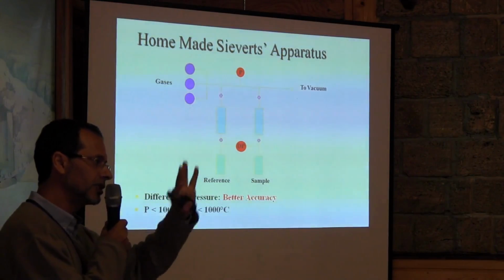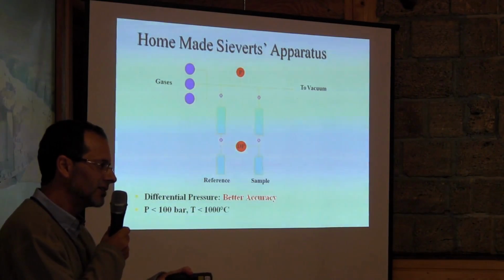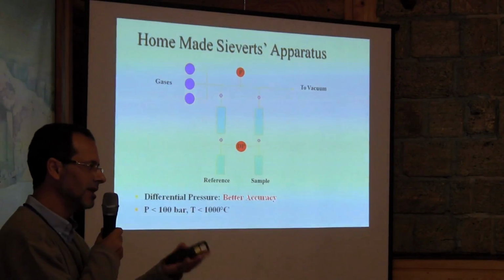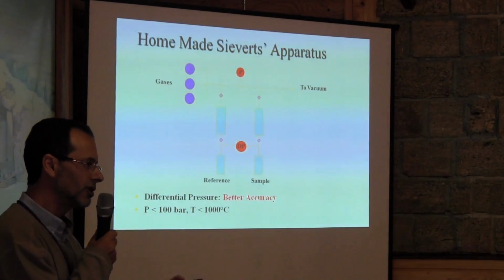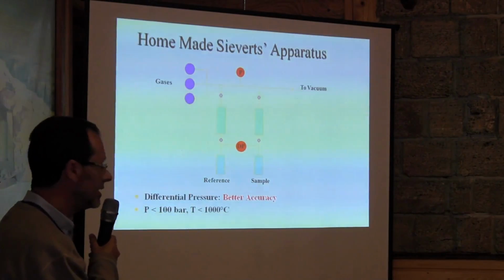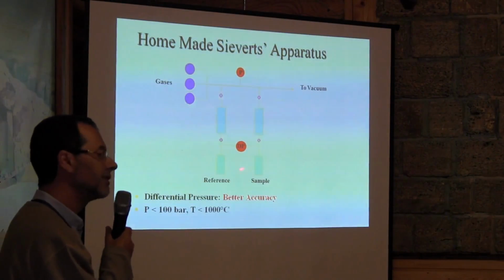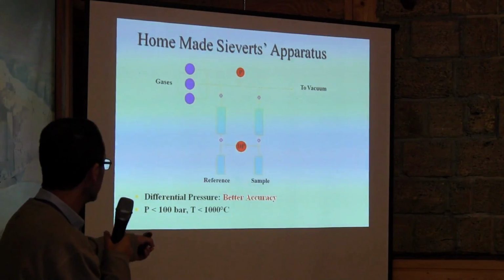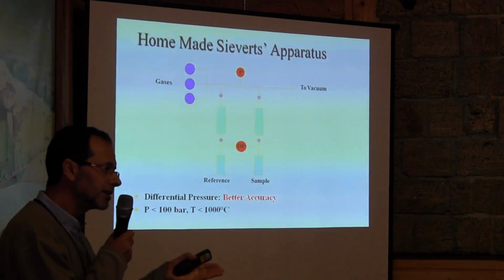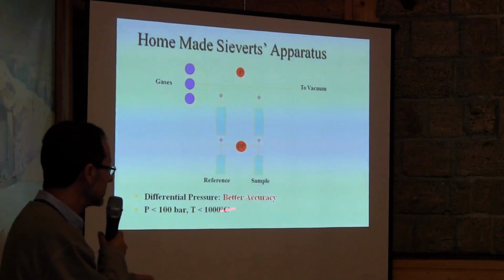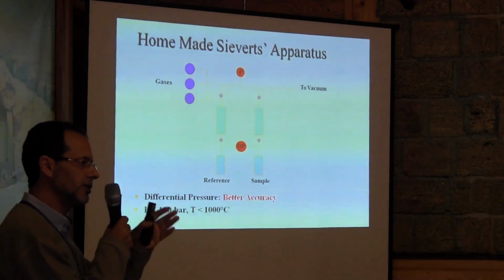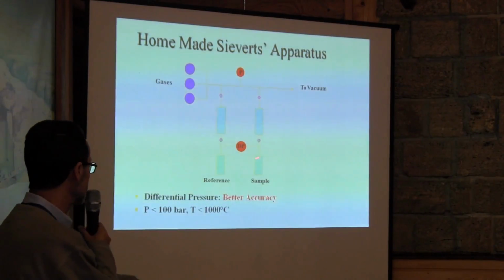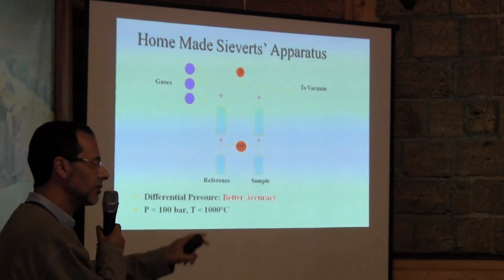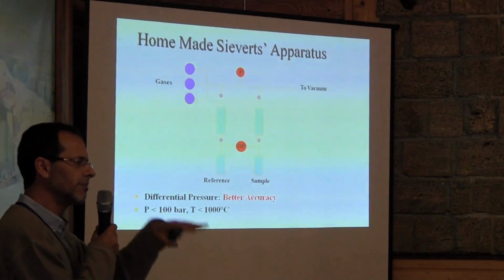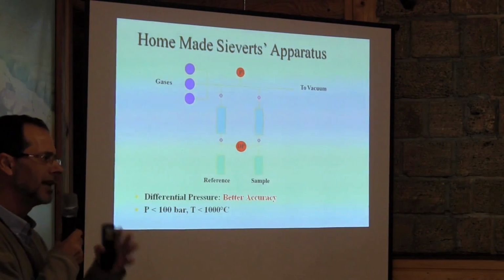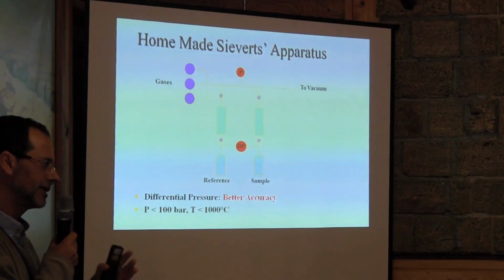that means the pressure changes. If I have a leak, what does it mean? I can measure hydrogen absorption, but finally it's not true, it's a leak. So it's a false reading. To avoid this problem, we also used a differential system. Some people use only one part, so if you have a leak, you measure the leak. But when you have a differential system, you have a reference and your material, and I measure the difference in pressure. So it's more precise. I try to improve the system as much as I can to have more accurate data.